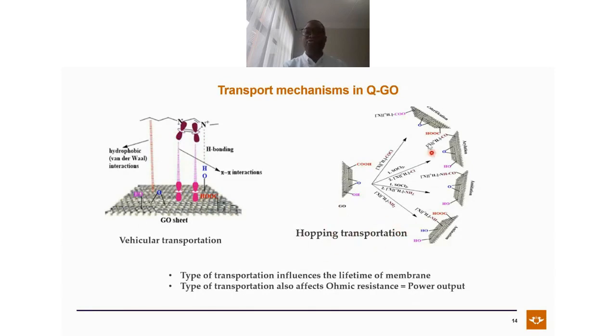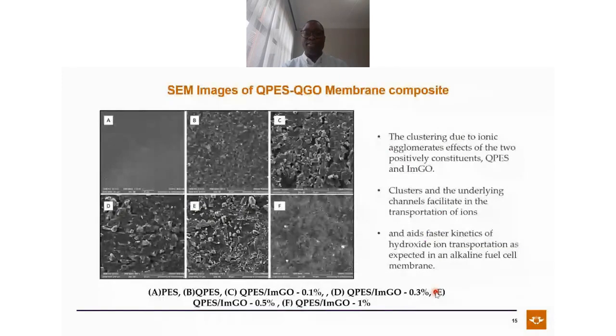The hopping method happens if your membrane is covalently bonded to the conductive material. So if we have graphene oxide, in our case we put in imidazole. We ended up having covalently bonded material, which was part of the amination. It was also able to conduct. So basically now this membrane has two modes of transportation. And this type of transportation influences how the membrane lifetime is going to be, and also influences the ohmic resistance, which influences the power output. Remember the ohmic resistance. Now keep in mind why that is important.